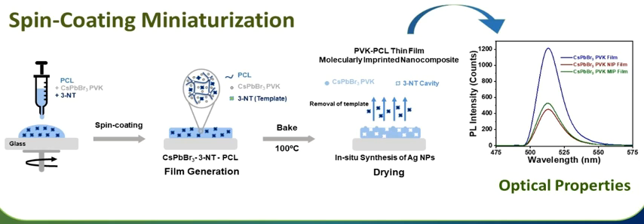in this graphic. The transduction mechanism of the cesium lead bromide nanocomposite is based on the high sensitivity of the PL of cesium lead bromide perovskite to local changes in their environment, for example when the analyte molecules are chemisorbed on their surface.